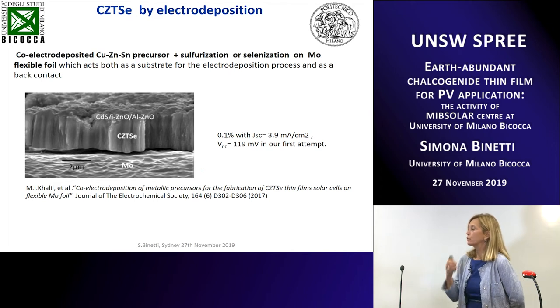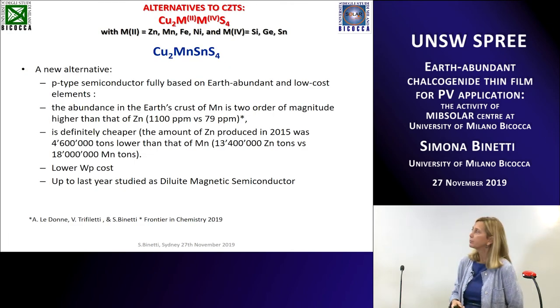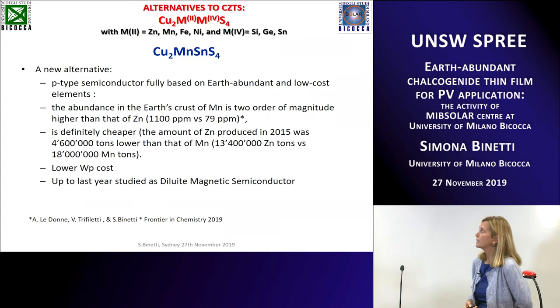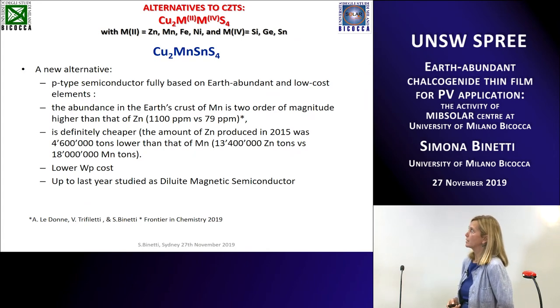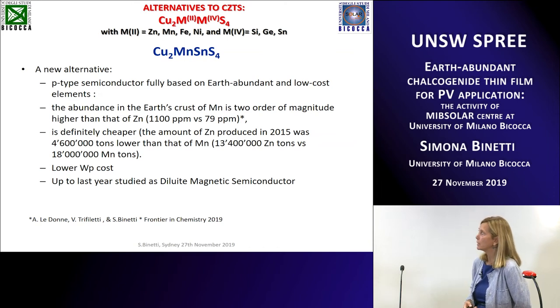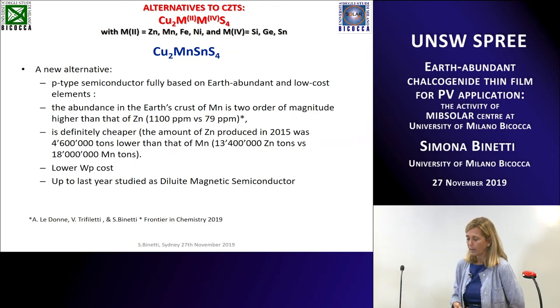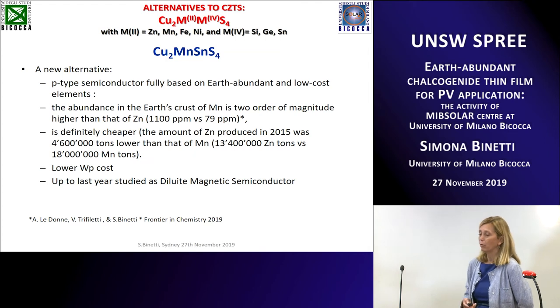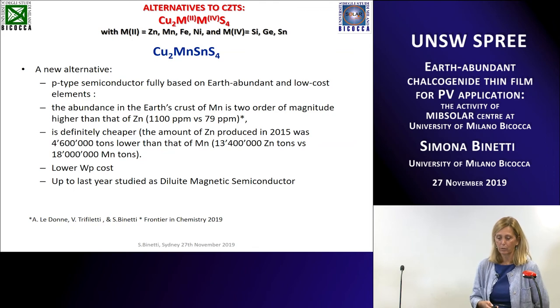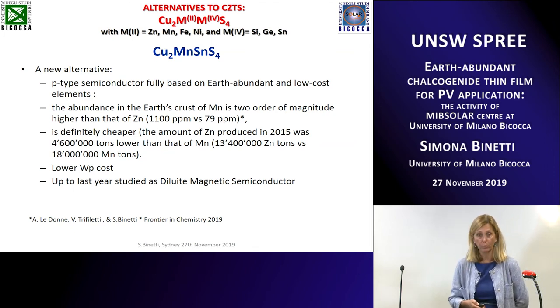Then we also decided to investigate an alternative to Kesterite, that is copper manganese tin sulfide. The idea is to replace zinc with manganese, because manganese has an abundance in the earth's crust that is two orders of magnitude higher than that of zinc, and so it's cheaper. And so in principle you can get a Kesterite-like solar cell with lower watt-peak cost. At the moment, this material has been studied only for its magnetic properties for spintronic applications, and there is just one group in the world, Professor Chen's group at the University of Shanghai, that is working on this material for PV application.